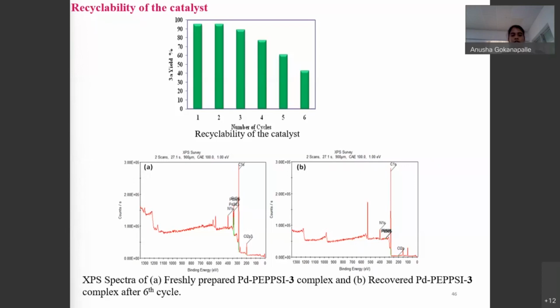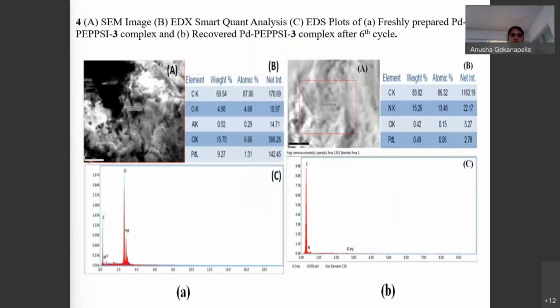This is the XPS spectra of freshly prepared palladium PEPPSI complexes and recovered palladium PEPPSI 3 complexes. Here we observed less intensity of palladium in the recovered palladium PEPPSI 3 complex. That is why we observed dropping of yields after the 6th cycle, as the palladium converts into nanoparticles. This is the EDAX spectroscopy of freshly prepared palladium PEPPSI and recovered palladium PEPPSI 3 complex. Here, palladium and chlorine content weight percentage was 15 and 9, but in the recovered palladium PEPPSI 3 complex, the palladium and chlorine weight percentage is decreased. That is why we got less yields.